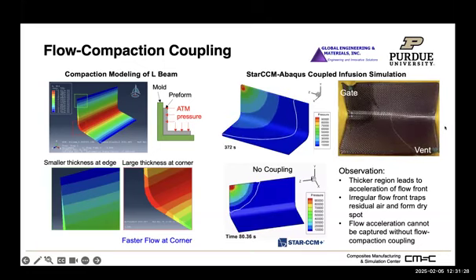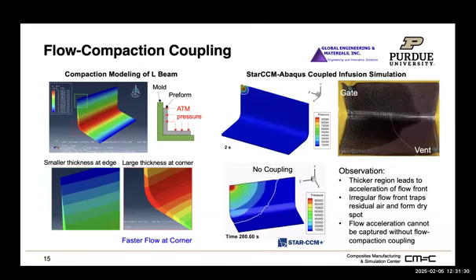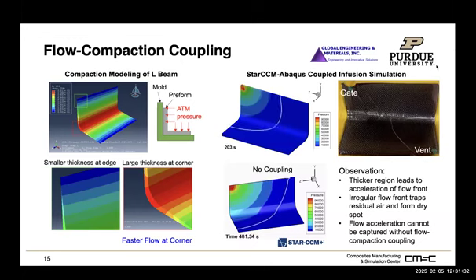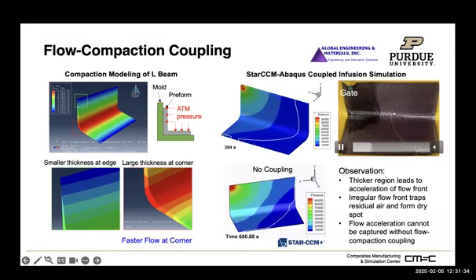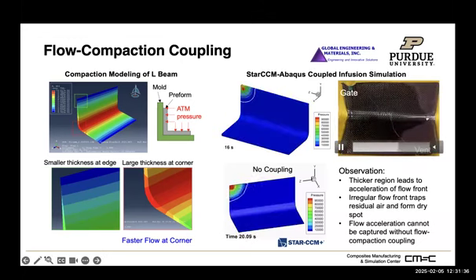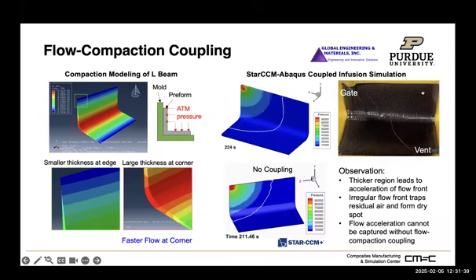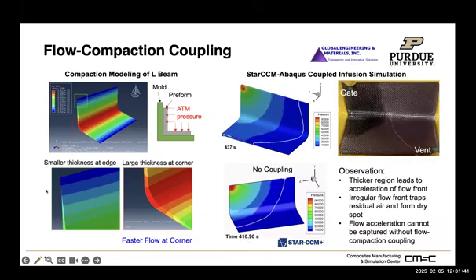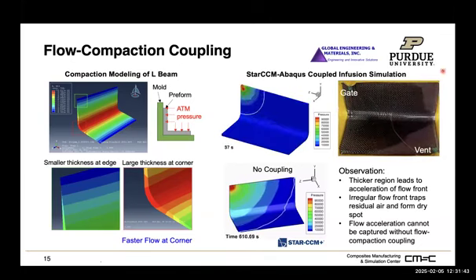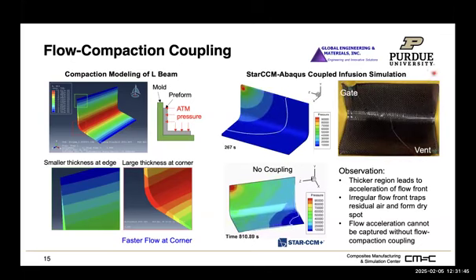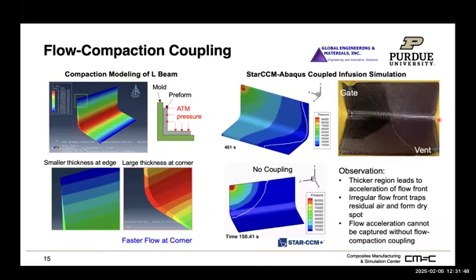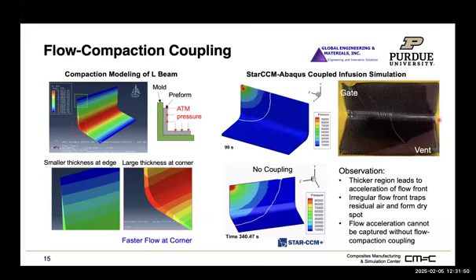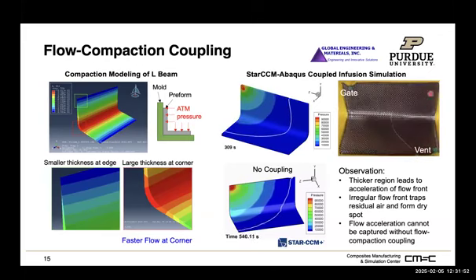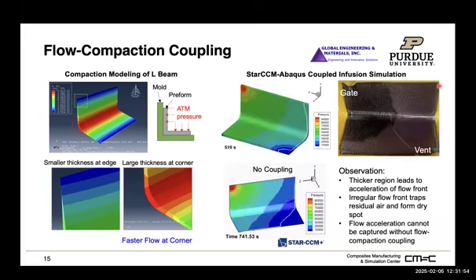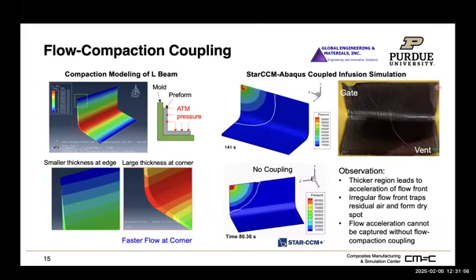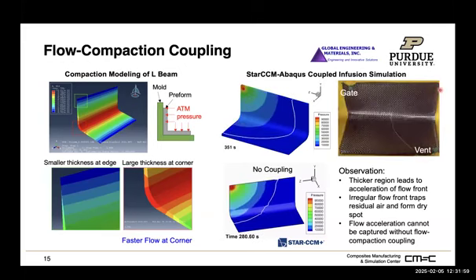This is something very interesting because we have been talking about defects so many times. What we observe from the experiment is if we get acceleration at the corner, the flow gets accelerated, and if you look carefully at the top corner, it enters with some dry spots because the resin is very hard to penetrate to that region and is only wetted by diffusion. So that will be a very slow process to fill those dry spots.